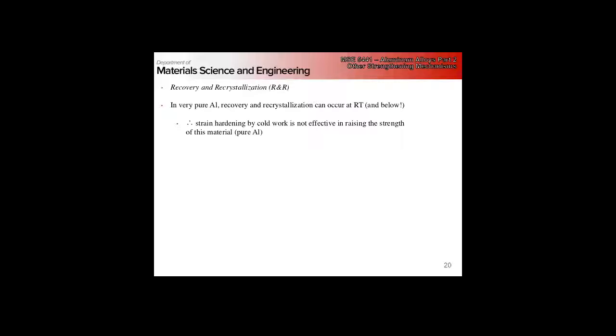Yeah. So because stacking fault energy is so high and dynamic recovery occurs generally, how is it that you're able to still see some dislocation rates or somewhat cellular structure? So very diffuse. Well, you still see it because you're not eliminating everything, okay. I mean, the fraction of dislocations that you remove during recovery is fairly small compared to the total dislocation content. Remember, you're still deforming. You're in dynamic recovery. You're still deforming plastically, so you're still generating, right? Dynamic recovery saturates when the amount of dislocations you're generating and the amount that you're removing balance, right? In static, you remove more, right? And you tend to polygonalize your grains, right? But you still don't completely destroy your substructure.